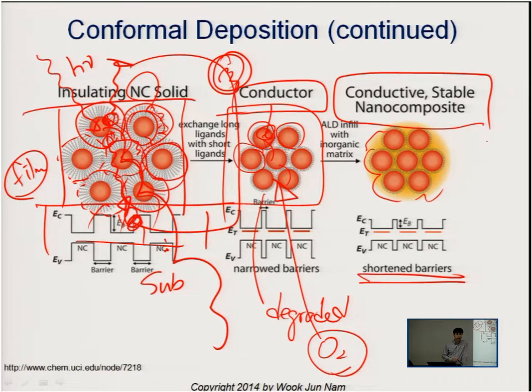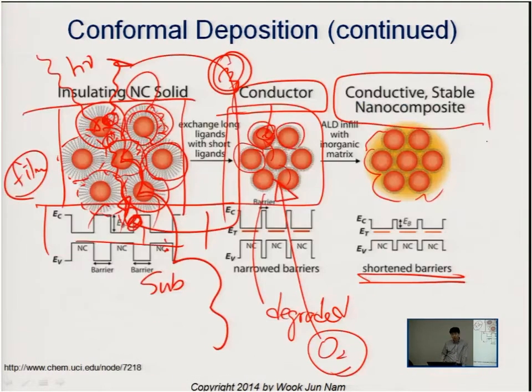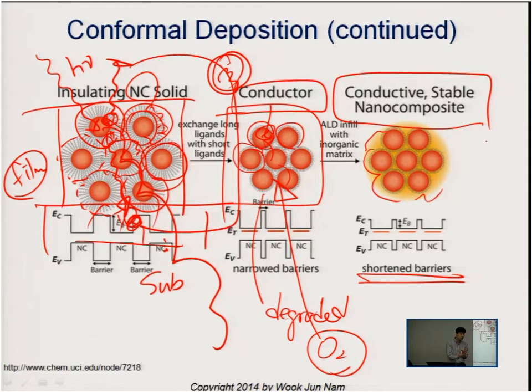materials using ALD. In this example, those materials should coat the individual quantum dots conformally. If the technique does not offer conformal coatings, even though we put an additional layer to protect the cells from oxygen, they will still degrade.